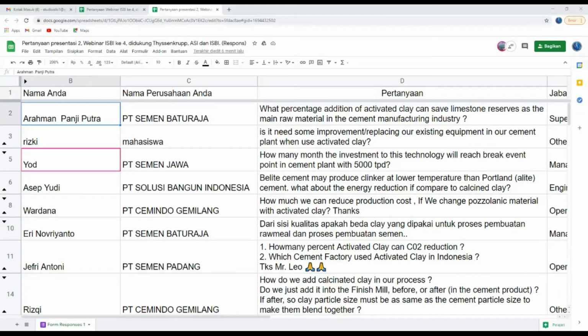So then there's the question on Belite cements, and what about the energy reduction if compared to calcined clay? So what I can say here is that for calcined clay production, we will need an energy of around between 500 and 600 kcal per kg. This is very dependent on the moisture level. So also here, just a rough estimate. And if compared to standard cement clinker, this is around 35 to 40% less in energy consumption. This we can say.